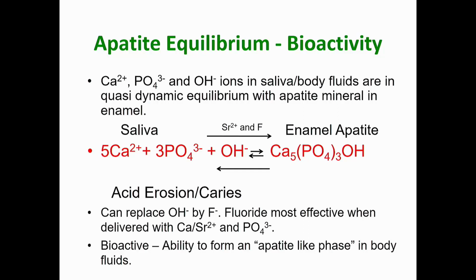But in dentistry, we also tend to add fluoride to things like drinking water or restorative materials. And this is because the fluoride ion can swap with the hydroxyl ion, and this pushes the equilibrium over in favor of apatite formation. But the apatite we now form is not hydroxyapatite, but fluorapatite. And the fluorapatite is much more acid stable and much more durable. And this is one of the attractive features of fluoride. It's also important to note that we can swap the calcium for strontium, and strontium also has a caries inhibitory role.